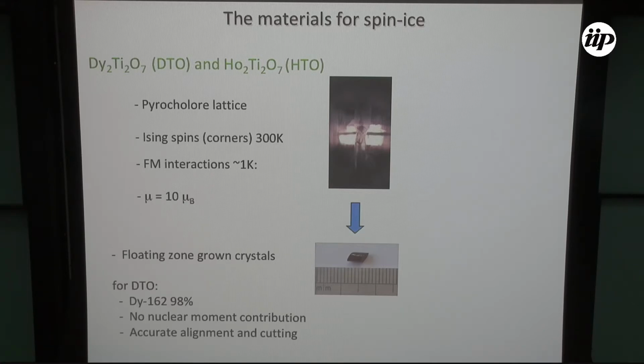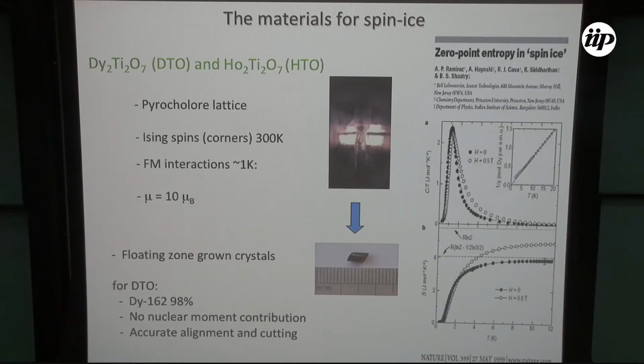So for the experiments I'm going to talk about, the neutron experiments and the heat experiments, we used an isotopic sample. The reason why we chose this isotope is not because of the cost, because the cost of this is something like 10,000 times the cost of non-isotopic dysprosium, but because these have no nuclear moments. So we wanted to have the cleanest possible sample, in the sense that we only wanted the contribution from spins, not spins from the nuclei. But the other reason is that dysprosium in natural abundance absorbs neutrons quite a lot. So if you want to do low temperature neutron experiments, you need to use some sort of isotope, otherwise they would heat up quite quickly.